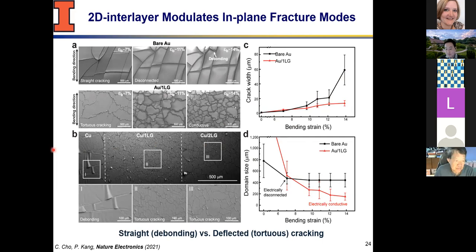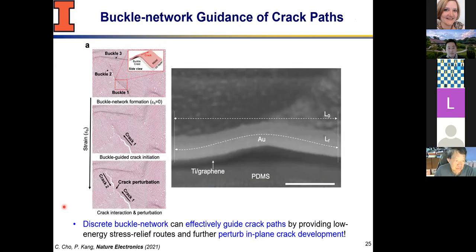So you might say, well, these might be two different processes. So what if you do it one time? So this is what we did. This is bare copper. We just put one layer graphene here, two layer graphene there. And that's what you see. Drastically different fracture surfaces, as we saw in the upper panel. So this is really something to do with what's underneath and how that affects this fracture and leads to this interesting behavior. So that's what we studied.